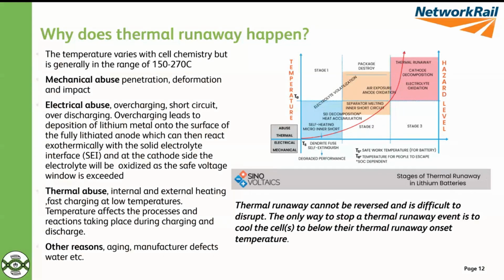So one of the main issues you can get is a solid electrolyte interface forming on the anode, which is a sort of surface layer that forms on the anode. And also you can get what we call lithium plating, where you get deposits of the lithium on the anode as well. And what that means, when I spoke about the lithium ions going into parking spaces on the graphite, the carbon graphite, with lithium plating and the solid electrolyte interface, they don't fit in the car parking space, so they just remain on the surface.